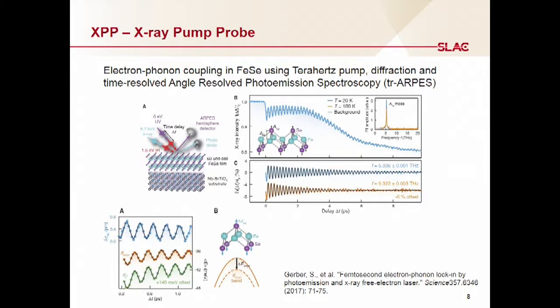What they did here is hit it with this terahertz pump, and then you can see the ringing of the lattice. This is the selenium atoms going back and forth. At the same time, they used a 6 eV UV probe in order to do ARPES, to look at what the electron momentums and energies were.